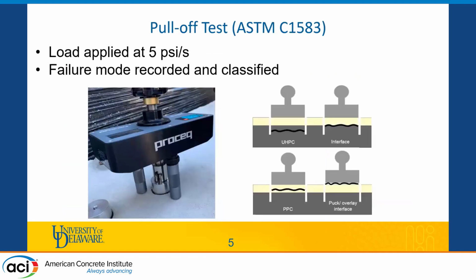To conduct the test, we use a metallic dolly that looks like this, and you have epoxy adhesive glued on top of the surface, and you attach that to the surface of your polyester polymer concrete. Then we use a pull-off tester to apply a tensile force of 5 psi per second.